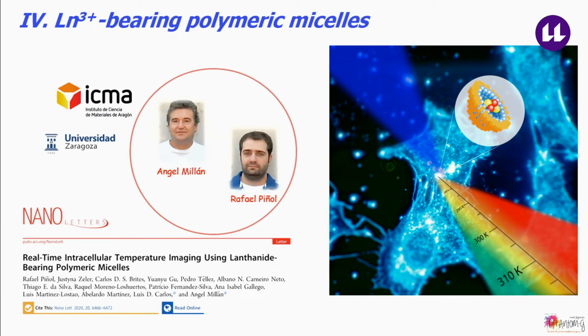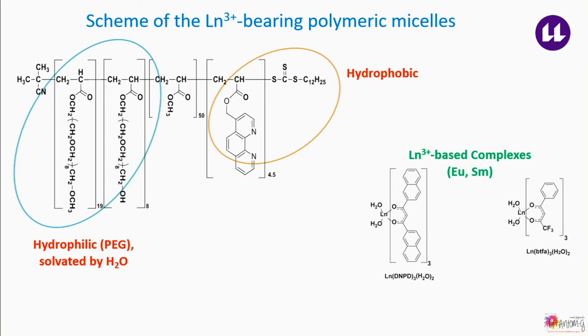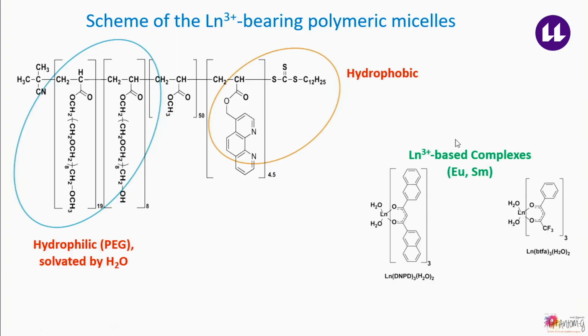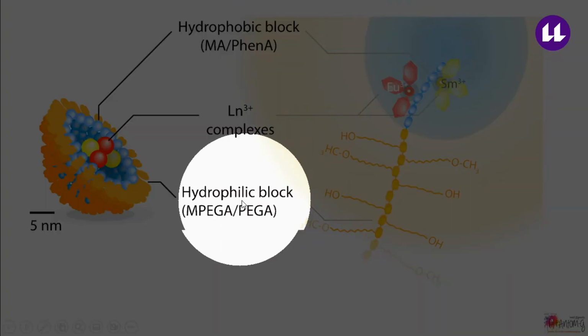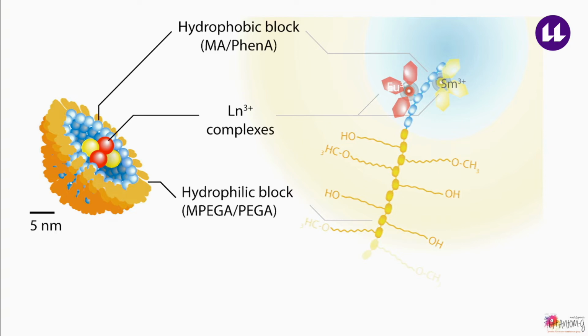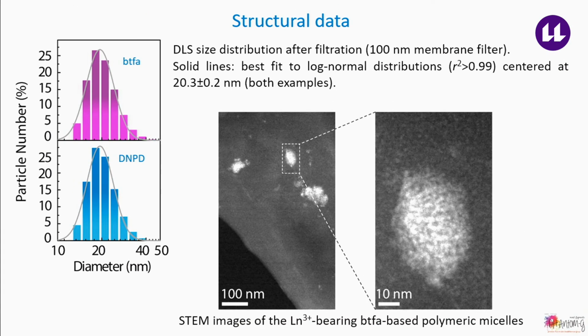In brief, as I mentioned, this is a work in collaboration with Angel Milan and also Rafael Pinol. We use polymeric micelles. The micelles have a hydrophilic and a hydrophobic part, and on this hydrophobic part we coordinate lanthanide-based complexes, complexes based on europium and samarium. Then we form this type of micelles, in which the light-emitting centers, the centers that we will use for sensing temperature, are very well protected from the interaction with the surroundings.